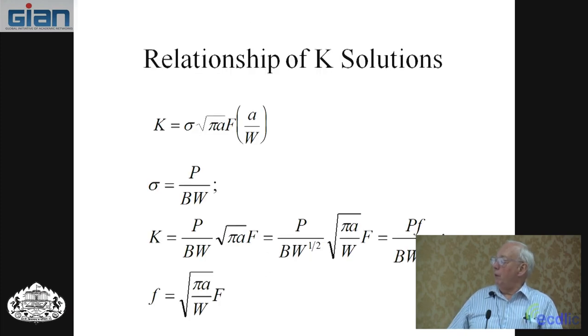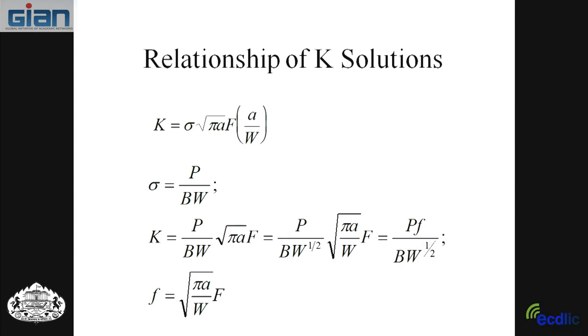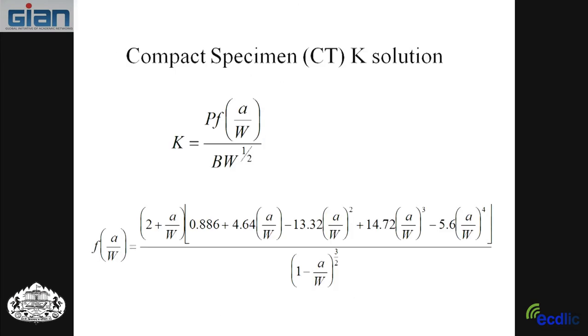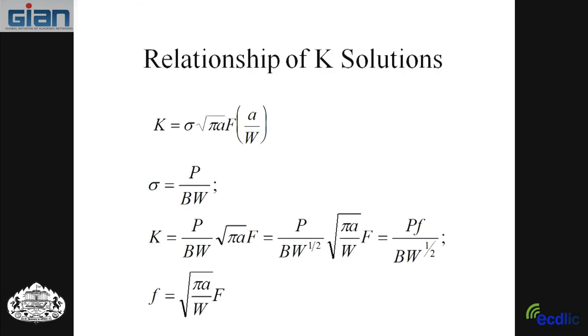Now the capital F form and the little f form are related. I just did the schematic so you could see, if you take the stress, it is load divided by the area, B is thickness, W is width. When we do K calculations, you're always calculating stress before the crack is in place. So you're taking a specimen like this, and assuming there's no crack in place and doing then the stress calculation for that. And then put that here for stress. Take the W and divide it into two square root parts, and then this whole thing here is the little f. So the little f is that whole thing. So they're essentially the same thing. However, if you start with stress, it's easier to use the capital F form, and if you start with load, P here is the load, it's easier to use the little f form.